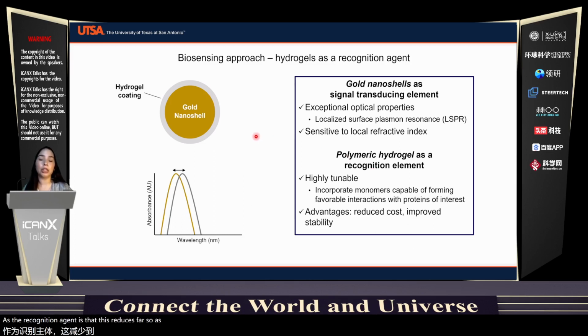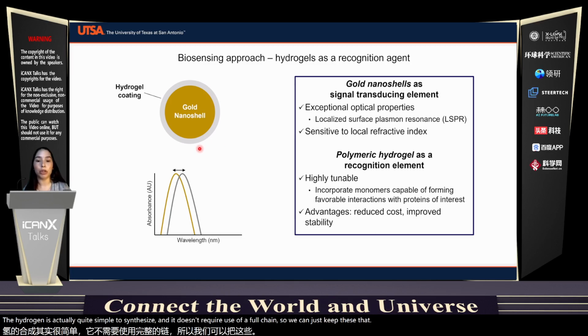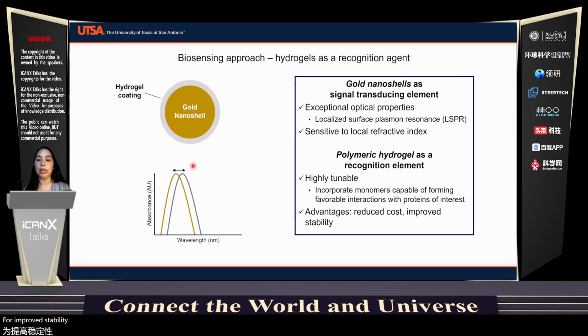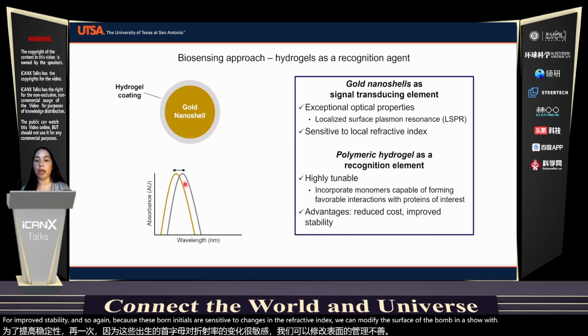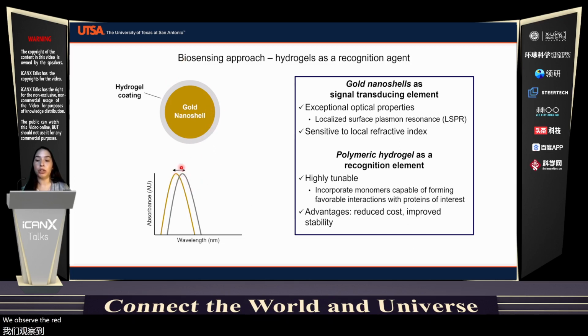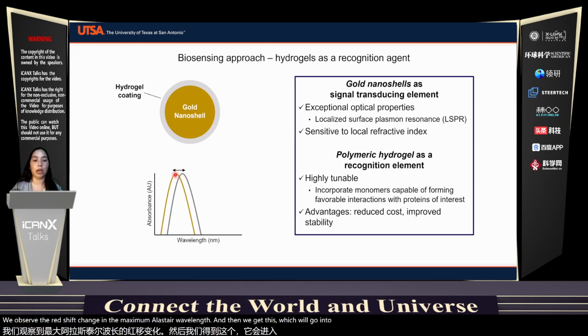Another aspect of using hydrogels as the recognition agent is that this reduces costs. So as an alternative to antibodies that require specific synthesis methods, the hydrogel is actually quite simple to synthesize, and it doesn't require use of a cold chain, so we can just keep these at room temperature for improved stability. And so again, because these gold nanoshells are sensitive to changes in refractive index, we can modify the surface of the gold nanoshell with a hydrogel coating. We observe a red shift change in the maximum LSPR wavelength, and then we get this, which we'll go into later, but this will be a delta, or change, in the maximum localized surface plasmon resonance wavelength.